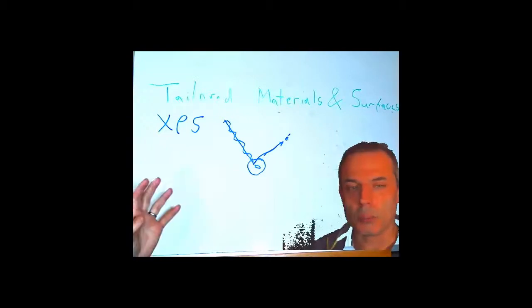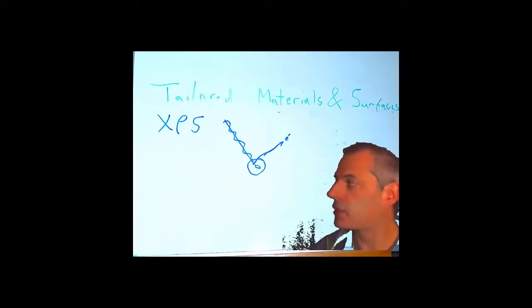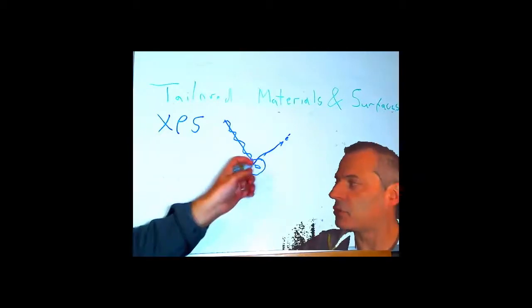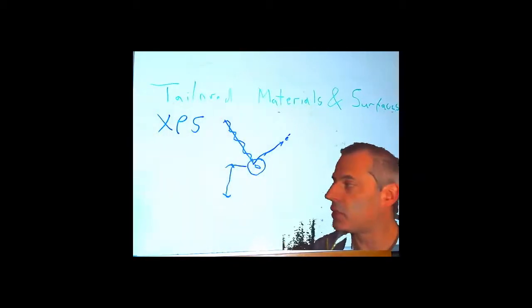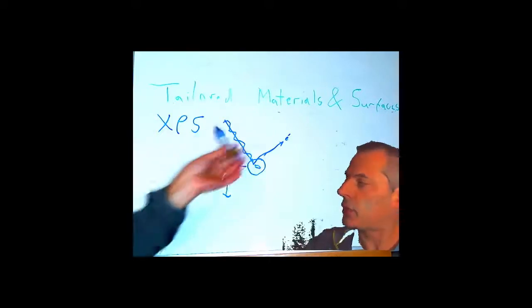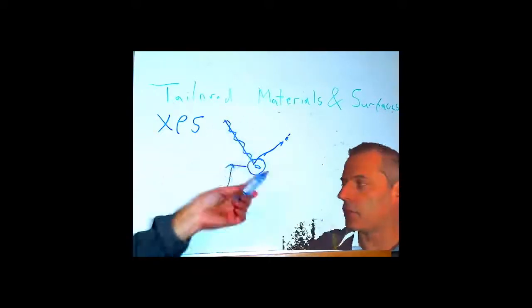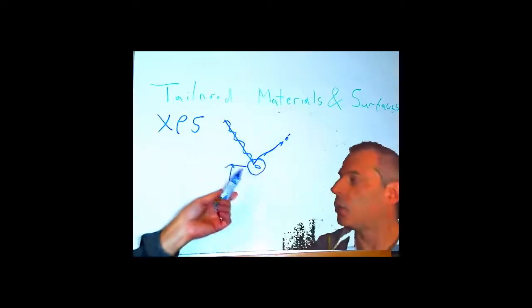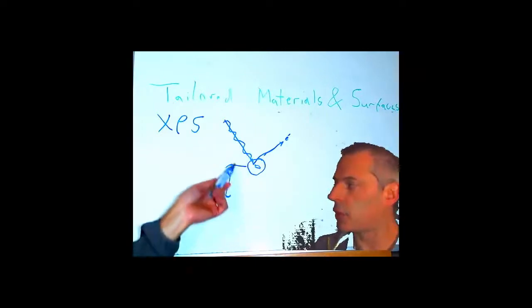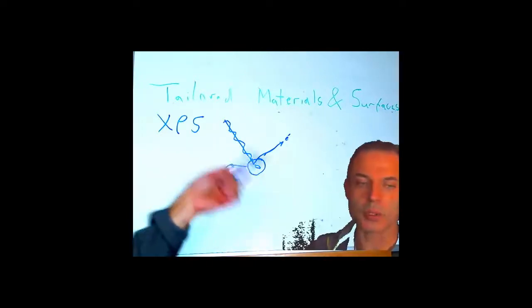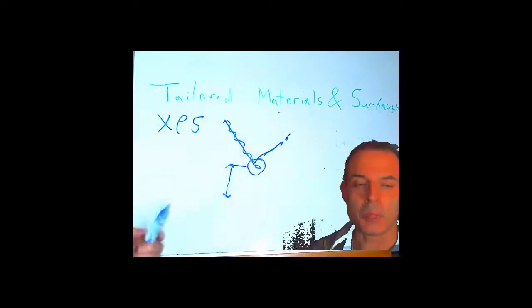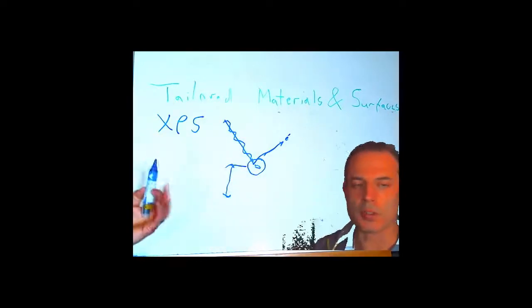What is important here, however, is our surface effect. So this only penetrates a few tens of nanometers, or actually more importantly, the electron can only escape a few tens of nanometers. And depending on the angle that we use to shoot it in, if we have a flat surface, we can control the angle by tilting our sample. We can reduce its effective depth by increasing the distance that the X-ray goes. It increases the distance that the electron has to escape through, and that means we get more surface sensitivity.